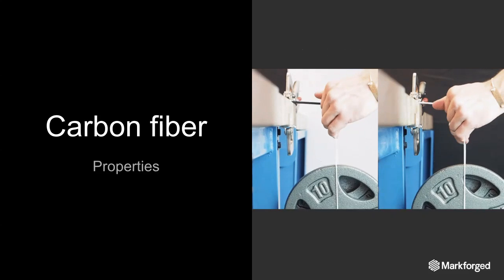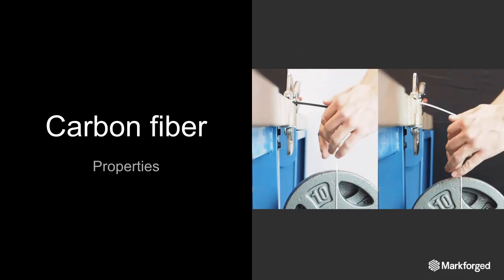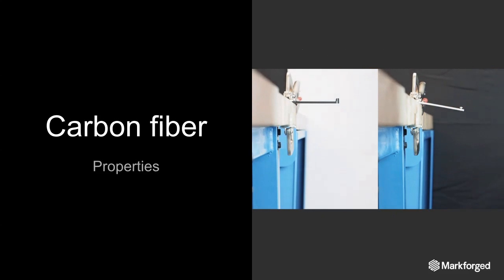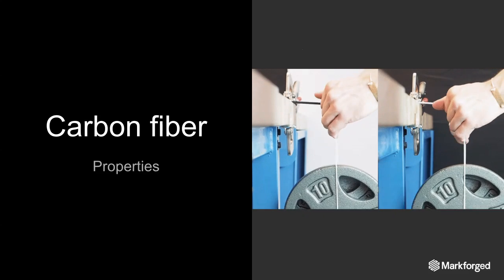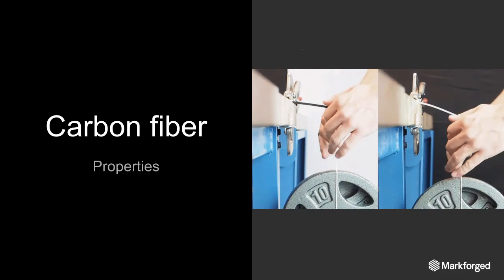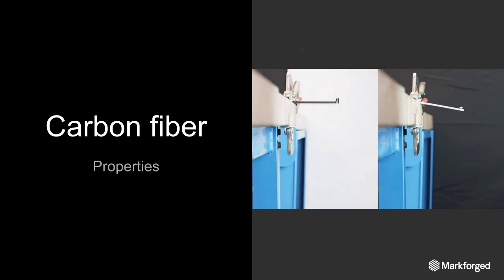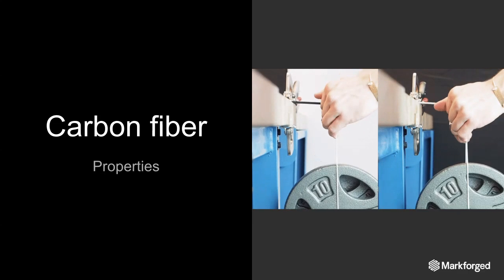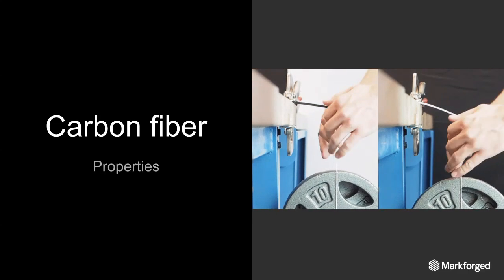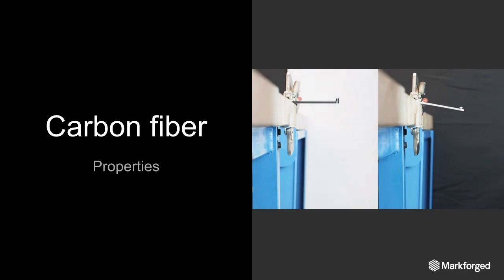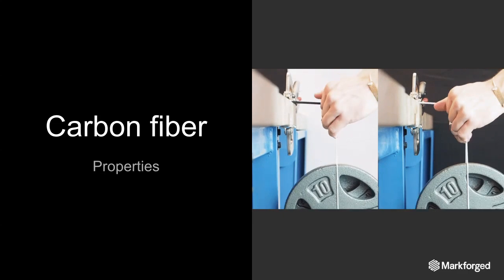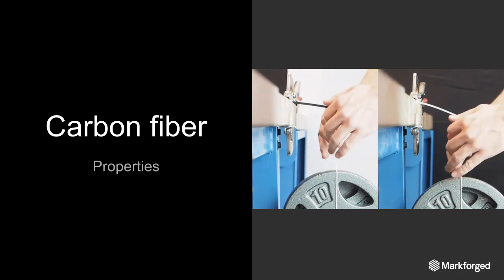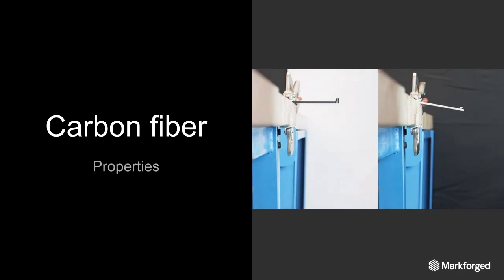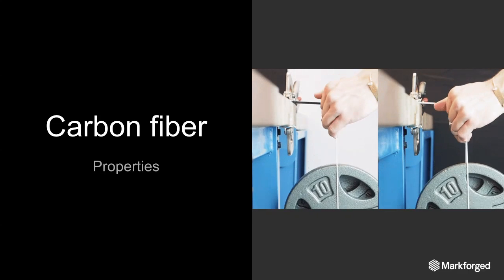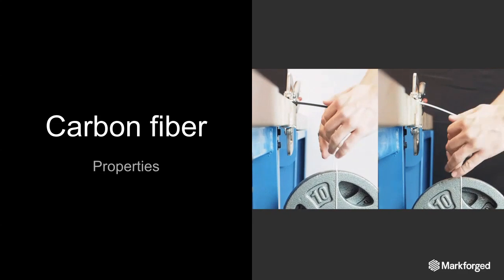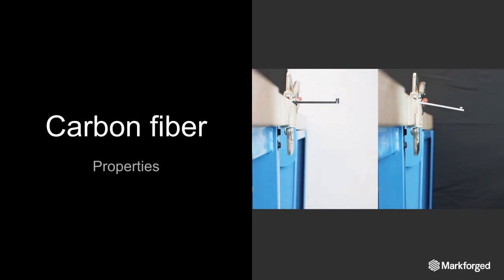So in this video, 27.5 pounds of weight is hung from a 7-gram carbon fiber beam. And then the same weight is hung from a 12-gram 6061 beam. You can see that the composite part deflects very minimally and then returns back to its original shape when that weight is removed. And that aluminum beam begins to yield as that weight is placed on it. And when the weight is removed, it doesn't return back to its original shape because it has started to plastically deform.